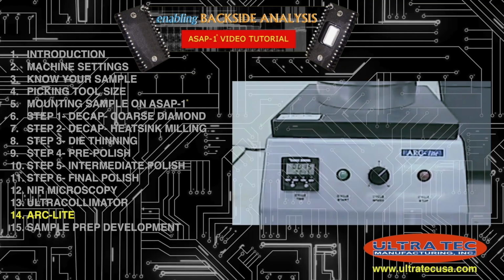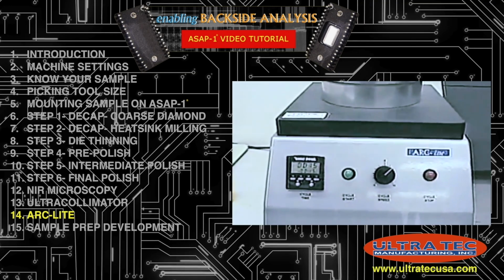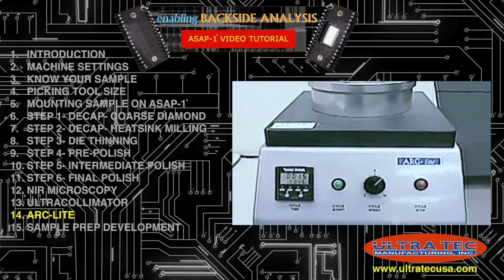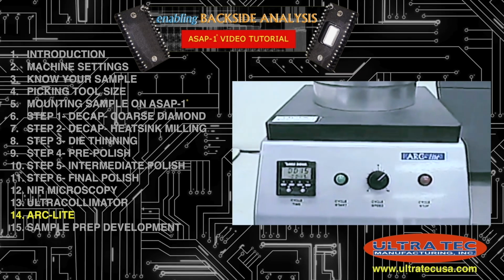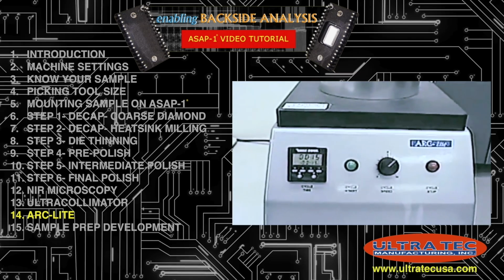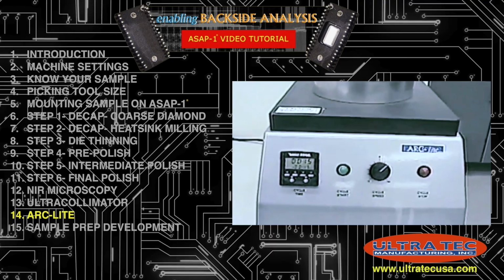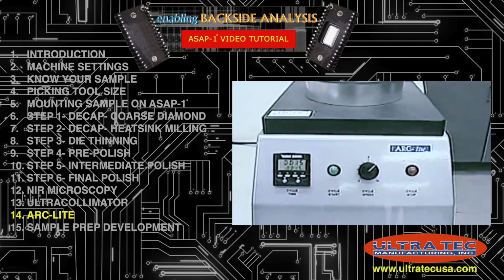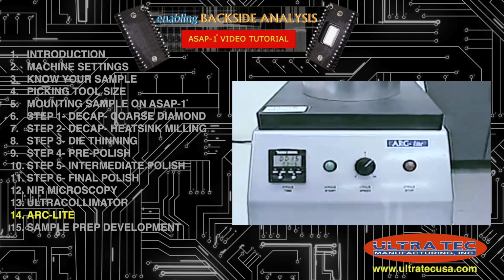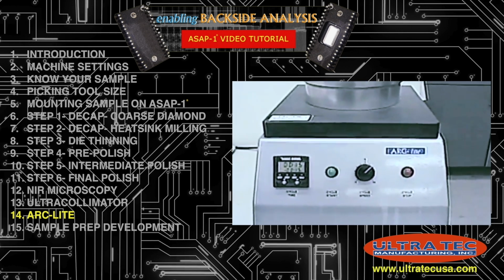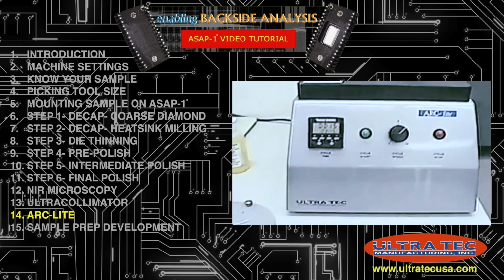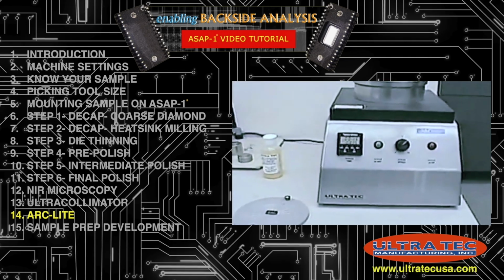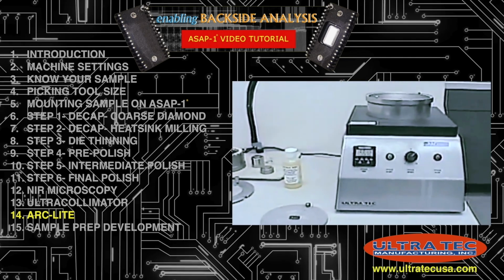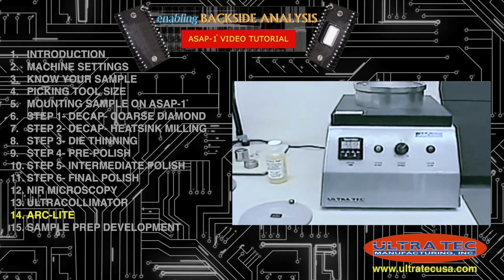ARC coatings improve the image contrast up to 60% on backside images. Emission sensitivity is improved up to 30%. This is helpful for emission microscopy and crucial for laser analysis. Key features of the ARC-lite system are that coating times are short, generally 45 seconds.